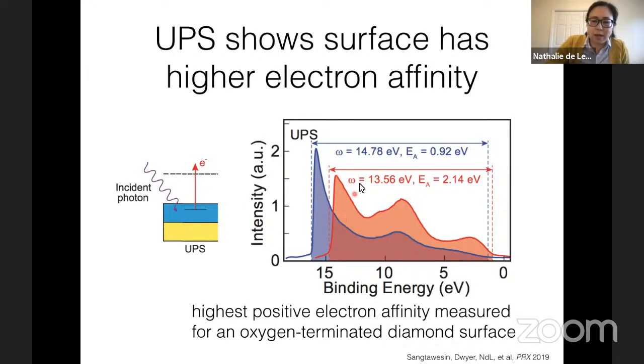And actually in doing this work, we solved a long-standing puzzle in the field, which was that if you did calculations of what the electron affinity should be for hydrogen terminated diamond, if you made it and compared it to calculations, you were basically spot on. But for oxygen terminated diamond, people generally saw this discrepancy of 1 to 2 eV. So what we showed is that the degree of disorder in the surface gives you a large number of electronic traps that really change your electronic structure enough to move your electron affinity around.